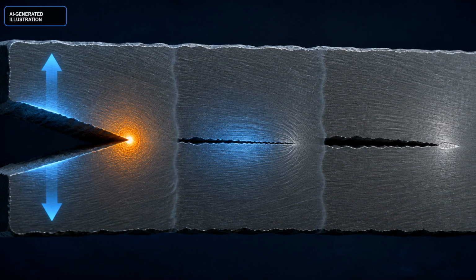Once several microscopic defects link, we have a crack. Pull the part and the crack opens. Near its tip, a very small plastic zone blunts the sharp edge. Release the load, and the faces close again. But closing is not healing. The new surfaces created during the opening step remain, and the crack tip can advance by a microscopic increment. Repeat the cycle, and the same sequence happens again. This is why a part can return to its original shape after each cycle, while its internal damage quietly accumulates.